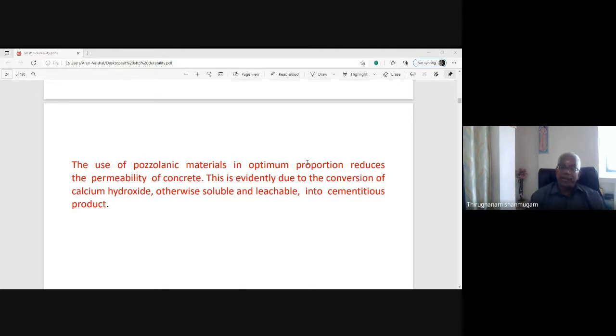About 20% or 30% of the cement is replaced by fly ash, about 40 to 50% of the cement is replaced by GGBS, and only 8 to 10% of the cement is replaced by microsilica, etc. That is the optimum proportion. The primary purpose is to reduce the permeability of the concrete. If the concrete is impervious, automatically the durability of the concrete is higher.